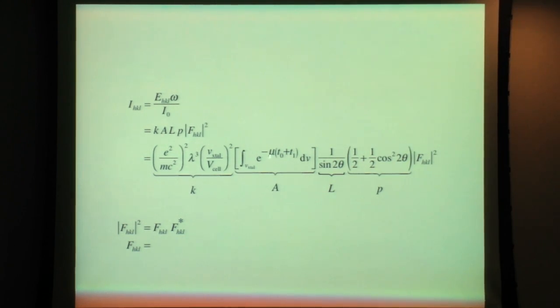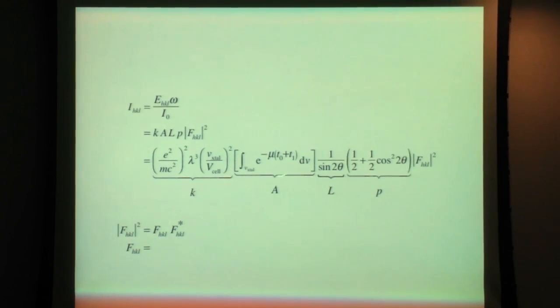So for each element, there is an absorption coefficient, and the longer the path of the beam through the crystal, then that coefficient multiplies the path length, coming in and going out. T0 for the incident beam, T1 for the scattered beam. Right? And these are quantities that are also tabulated.